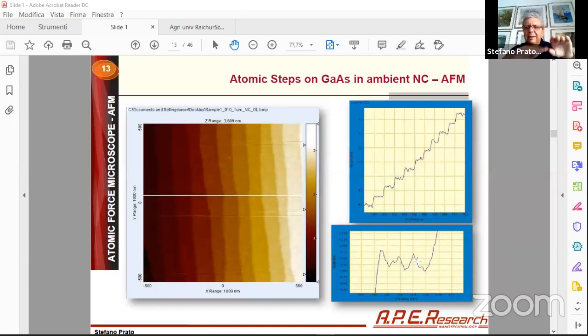This is some undulation because this crystal, when it's exposed to air, gets oxidized. So the oxide is not atomically flat, but is a little bit waving. Okay, if we measure this wave, it will be about 40 picometer. It means 0.04 nanometer. It is less than one atom diameter.